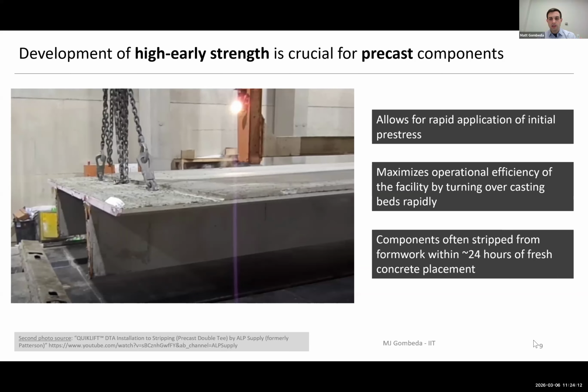And we also have to apply for pre-stress members, the pre-stress strands have to be released before we can remove it from the formwork. So now we have to design for early age compression as the pre-stressing is applied. And we also have to design for early age flexural strength because when the member is lifted out of the bed, it wants to deflect under its own self-weight. And generally, the number that people have targeted is 3,500 PSI compressive strength within 24 hours or less. And that number has only gotten more stringent as they try to be more efficient with different designs. So it's kind of like a baseline minimum at the very least.